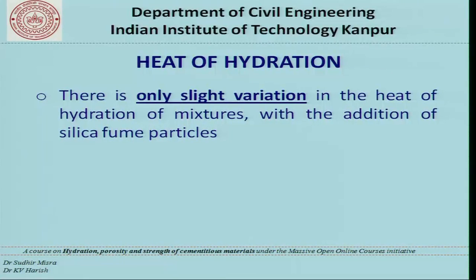Heat of hydration shows only slight variation with silica fume addition, primarily because silica fume is used at lower dosages of 4–12% compared to fly ash or slag. The amount of cement removed from the system is relatively small, so heat of hydration is not substantially changed. For applications where heat of hydration is critical, silica fume may not be the best option.